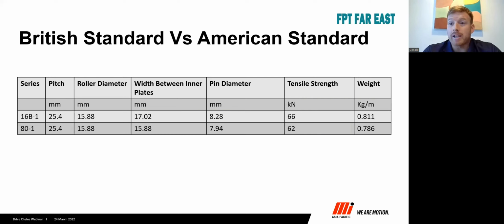So which one is better? The pitch is the same, the roller is the same, but then the other values are different. And effectively, the 80-1 is usually a more economical chain. It's slightly cheaper than the 16B because there's less material used. But then with your tensile strength, you have a sacrifice. And also your pin diameter is slightly smaller, so your wear life is also reduced, because if you can increase the pin diameter, you can increase the lifetime of a chain generally.